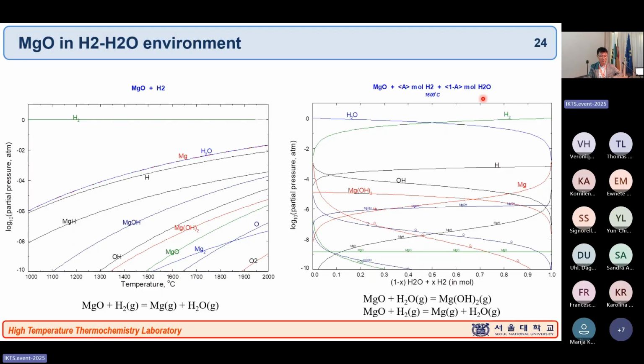Now how about if we change H2 and H2O gas simultaneously? Because if you are using H2 for something, some chemical reaction will probably always make H2O. So we sometimes have to look at both H2 and H2O conditions simultaneously. With magnesium here, H2 condition here, and this is the H2O condition. Under the H2O condition, as Jung also said, Mg(OH)2 can be formed at low temperature as a solid, and at high temperature as a gas phase. It is not enough to make pure Mg(OH)2, but you can see about 10 to the minus 5 partial pressure of Mg(OH)2 can be formed. If you go to higher temperature, you can see this going up, and you can start to have degradation of the MgO refractory by H2O.